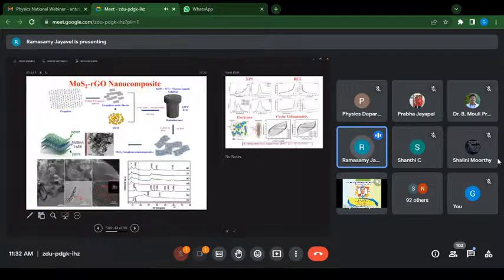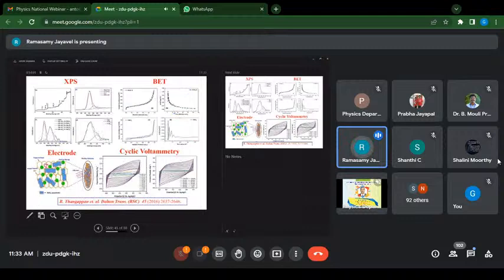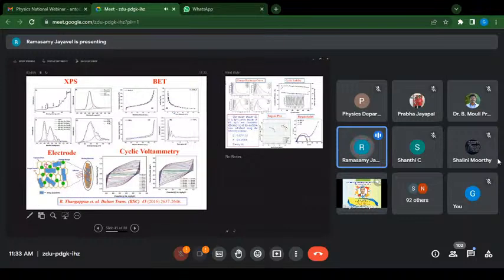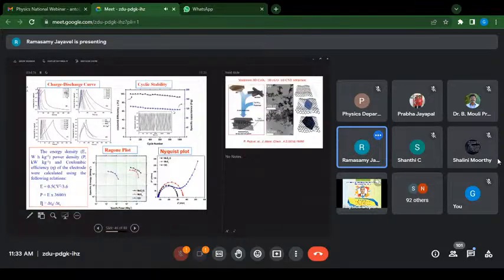So this is actually the electrochemical property. Then we also tried to make heterostructures of two different 2D layers, like MoS2 and RGO. This is the schematic where you have graphene, molybdenum disulfide, graphene alternate layers, which was also synthesized by a hydrothermal process. These electrodes also had a very high current density of the order of ampere per gram, which can be useful for achieving a higher specific current and power density. And the charge retention after the charge-discharge cycles is also highly stable.